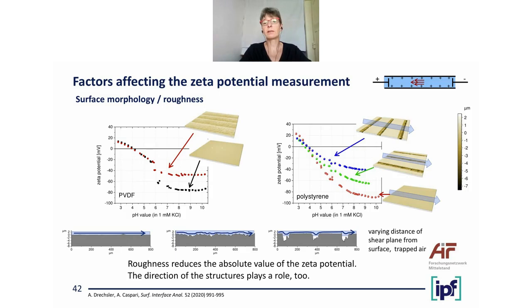But if you have a look at the schemes at the bottom, you maybe can imagine the reason for that. According to theory, we have a defined shear plane on a very smooth and flat surface, and the shear plane is always at the same distance to the surface. But if we have a rough surface, of course, the liquid flow or the shear plane is not always at the same distance to the surface, and you may also have entrapped air in some voids, and that's why not all of the surface is accessible to the Zeta potential, and that's why the absolute value becomes lower.